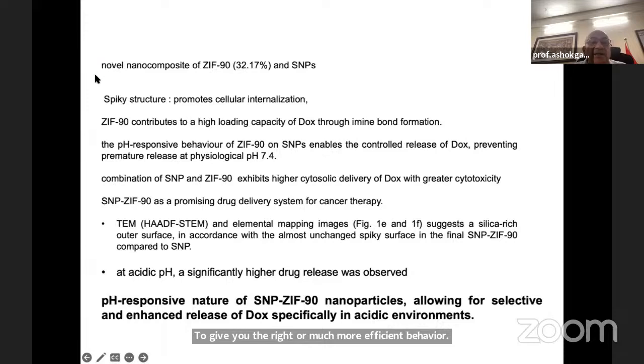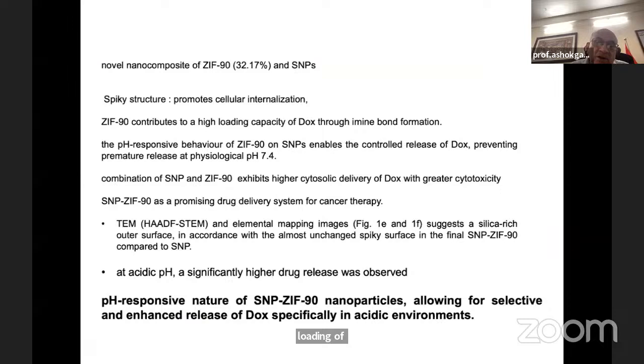It helps cellular internalization. It allows high loading of doxorubicin through imine bond formation. Okay. So there's an amino group in this doxorubicin. This drug has an amino group, and there is an imine bond formation. That's the chemistry actually which we use. And the important thing is that it releases drug at 4.5 pH, not at 7.4, which is the physiological pH. And we can show using characterization, using microscopy, etc., how this nanoparticle allows selective and enhanced release of doxorubicin, especially in acidic environment. So this is one paper which we published.